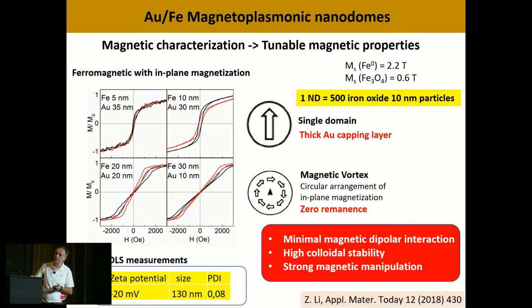But when we have thicker iron layers, like 20 or 30 nanometers, you see that the hysteresis loop changes. And now what we have is what is called a vortex structure. Instead of having all the moments pointing in one direction, as you would expect, now, due to the competition between magnetostatic energy and exchange energy, the most favorable state is one where the magnetic moment rotates around the circle of the particle. And in this way, you have zero moment at zero field. As we can see here in the hysteresis loop, they have zero moment at zero applied field. That means that these nanoparticles at zero field don't interact with each other, so they do not agglomerate.